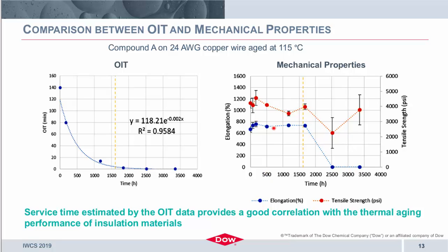Now, if I tried to translate that into the mechanical properties, you actually see that at that same time period in the right-hand plot, you would not pick up that difference in the mechanical properties. So if you were to rely on one or the other, you would not be predicting the same behavior. And so it's important to couple them together if trying to estimate given service times, or even looking at performance over time, where you need to combine multiple measurements to make sure that we're giving ourselves the best chance of predicting longer term performance when accelerated conditions are considered.